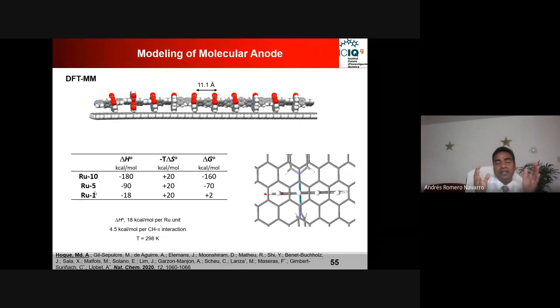But this pentamer is still one molecule, right? So it will have almost the same entropy effect. Now if you couple them, you get this delta G value, as you can see here, of minus 70 kcal per mole. So with the mononuclear compound, it was not going to stay, but if you have 5 units, then the energy suggests that this 5-unit molecule can stay. And if you increase the number of units even more, like 10 or 15 units, you can see that this delta G value is getting more and more negative, suggesting that the system is becoming more and more stable.